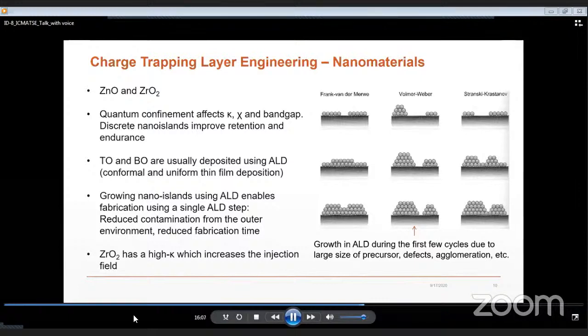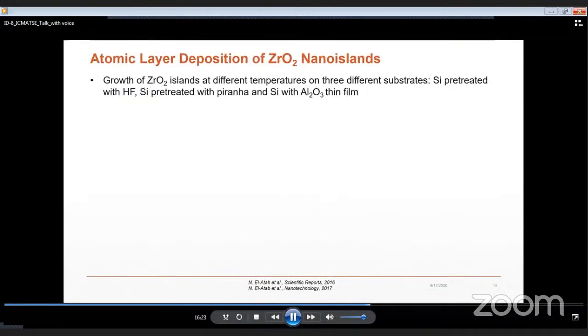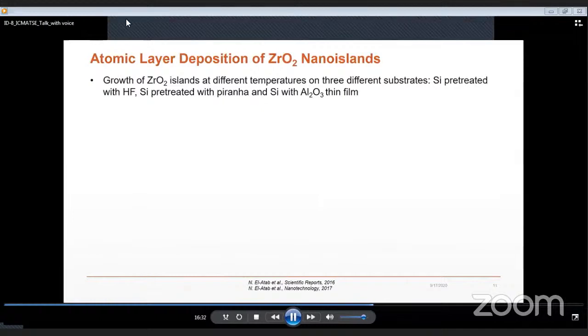However, we have shown that by changing the growth conditions and the substrate termination, we can get nano-islands instead of continuous films during the first few deposition cycles, following the Volmer-Weber growth mode. The first material that I will talk about is zirconia. Zirconium dioxide is chosen because it has a large charge trapping density and a high K, with large band offsets with the tunnel and blocking oxides when aluminum oxide is used.